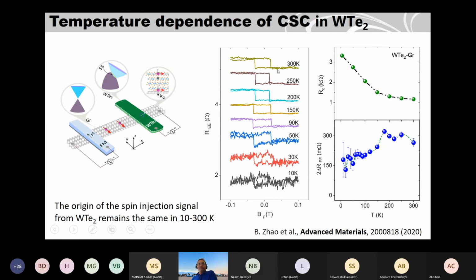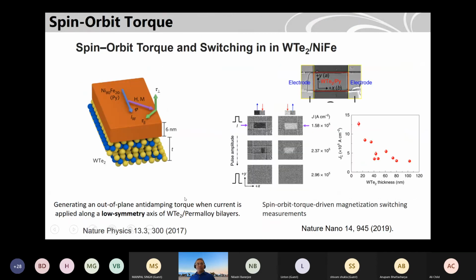So it is quite good for applications. Here we also cool down the sample to very low temperature, and up to 10 Kelvin we also see the same signal, and that means the origin of the signal is the same from room temperature to 10 Kelvin. But the signal is getting a bit noisier at low temperature. That is because the interface resistance between tungsten telluride and graphene is increasing at low temperature, so that contributes to the signal noise. But the magnitude of the signal, I would say, is not changing much. So that means whatever the spin polarization, from wherever it's coming due to this spin charge conversion, it survives at all temperatures up to room temperature.